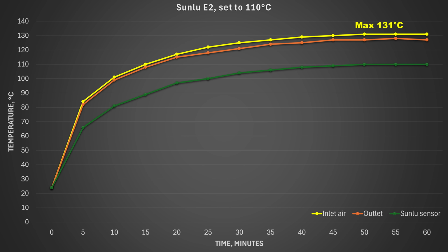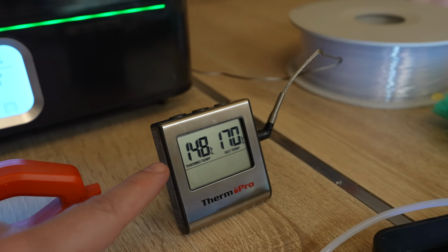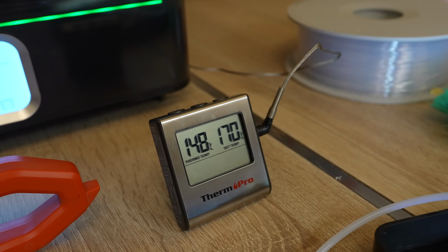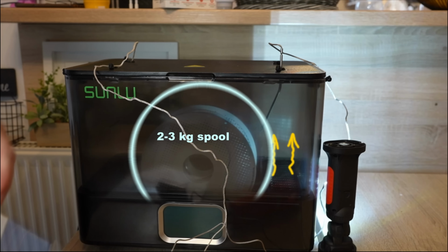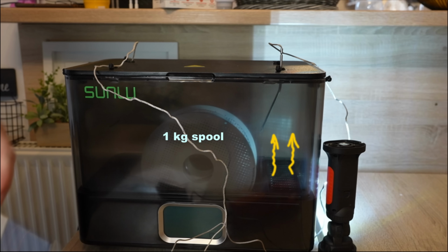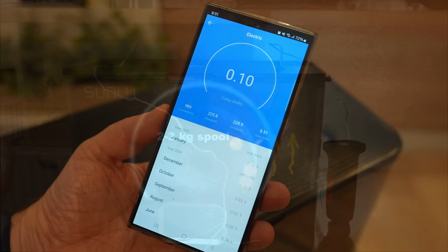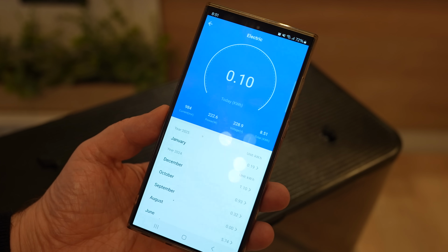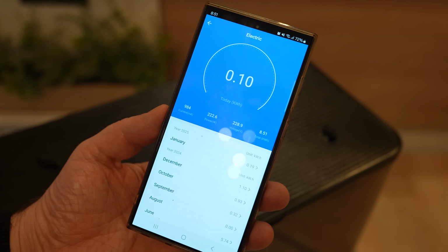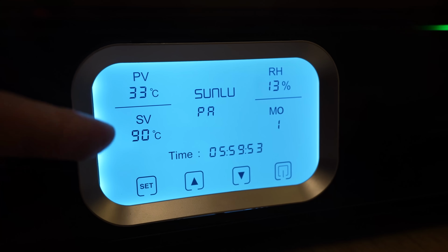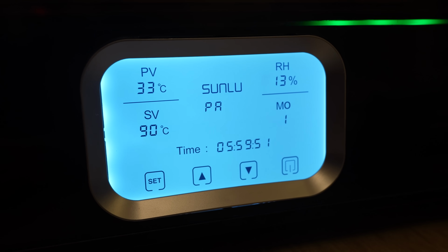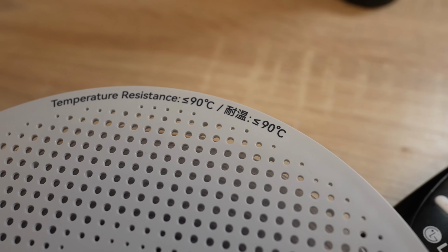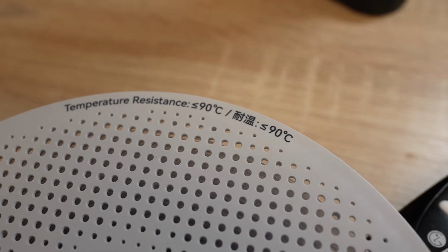But what I really worry about is that the maximal air temperature in this case was 148 degrees Celsius, and if you are using a 2 or 3 kilogram spool inside, this air will touch this filament. After 1 hour set to maximum temperature, the power consumption was 0.1 kilowatt hours, which includes the heat up time too. Now let's set the temperature to 90 degrees Celsius and see what will be the temperature of the air which touched the filament.